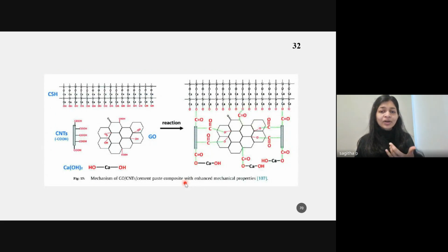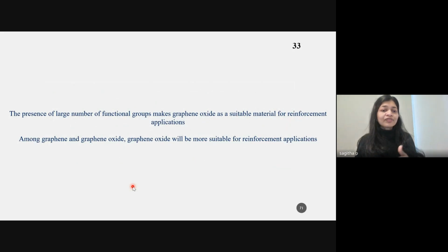So this is one of the works in which it is used for cement applications. Graphene oxide and carbon nanotube together were used as the filler material for this application. So they incorporated the carbon nanotubes and graphene oxide into the cementitious material, and they could provide some kind of interaction between the silicate particles and these filler materials, enhancing the mechanical properties. And the presence of a large number of functional groups makes graphene oxide a suitable material for reinforcement application as well.